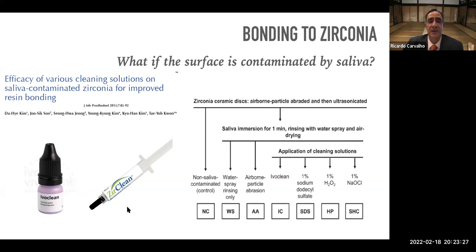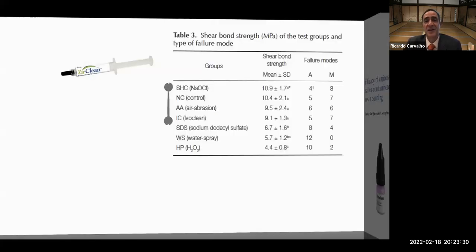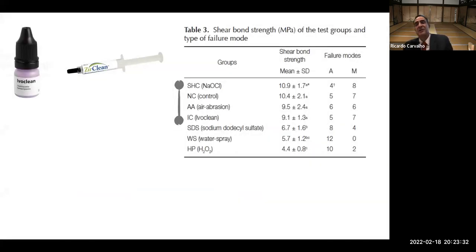They already prepared and created products that are based on these alkaline solutions in order to decontaminate the surface. And I tell you, regardless if you use Ivoclean, ZirClean, or some of these other products that are available in the market, might have some in Iran that I'm not aware of, they are effective. They are alkaline solutions, as we can see here, when we apply alkaline solutions or when the surface was not contaminated, we were able to get, or they were able to get similar results.